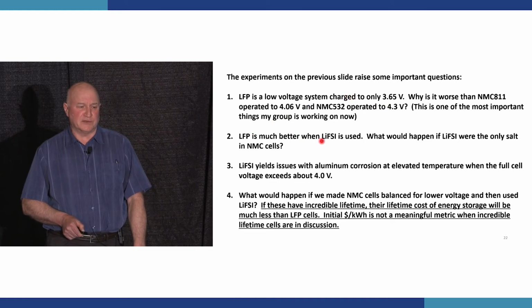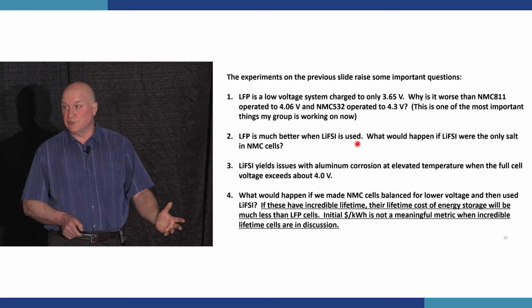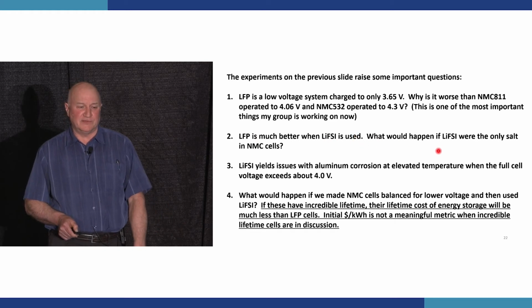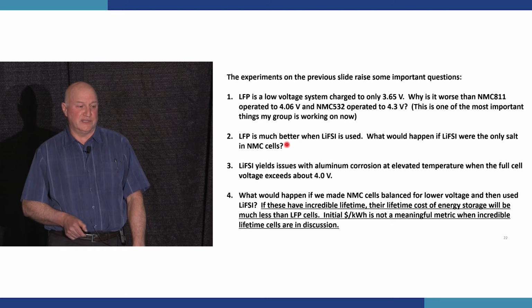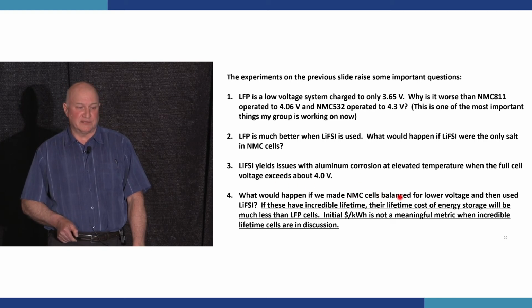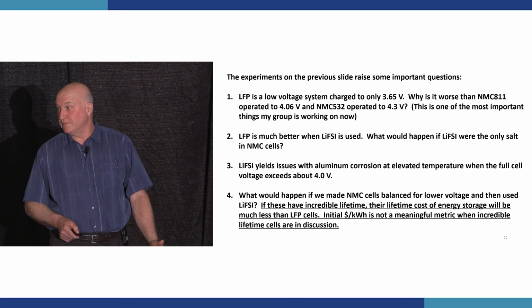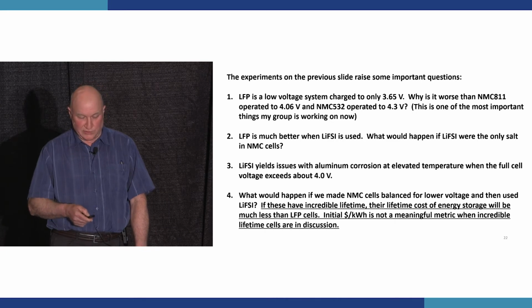LFP is much better when LiFSI is used. I showed you that. What would happen if LiFSI were the only salt in NMC cells? LiFSI yields issues with aluminum corrosion at elevated temperatures when the full cell voltage exceeds about 4 volts. Okay, so what would happen if we made NMC cells balanced for lower voltage and then used LiFSI? What would happen to their lifetime? Let's take a look.